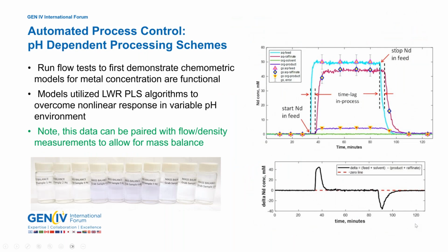The next slide shows the results of this experiment, where at the beginning, up to about 35 minutes into the experiment, we had no neodymium in the feed at all, and we were reading 0 concentration. This is the axis of concentration of neodymium measured by our model at the different locations. We're measuring 0 concentration for the aqueous feed, aqueous raffinate, organic solvent, and organic product. But at 35 minutes, when we added neodymium into the feed, we saw an immediate increase in the concentration at that feed location. Within a few minutes of that, we saw the concentration of neodymium in the aqueous raffinate increase, just like we saw the spectra increase in the last slide. We're interpreting that with our chemometric models, and we're seeing the neodymium coming out in the raffinate, likewise in the organic product.